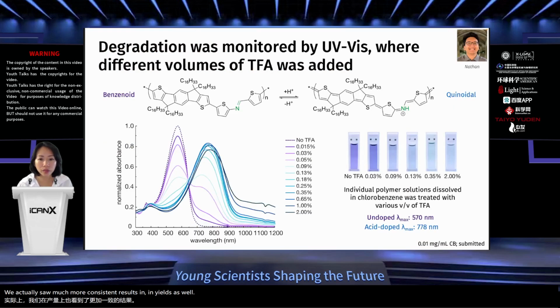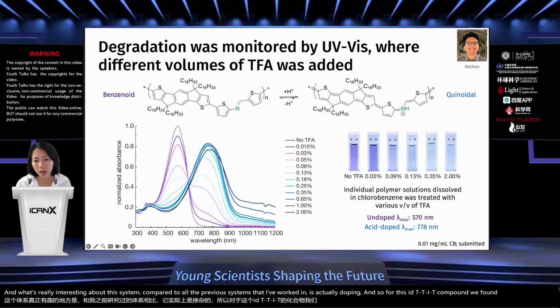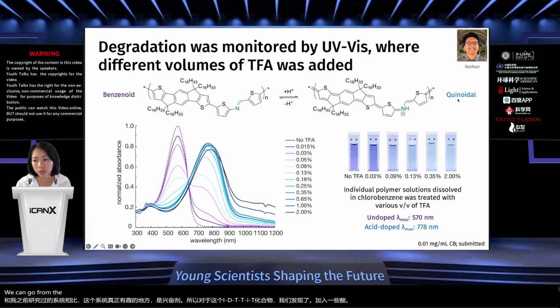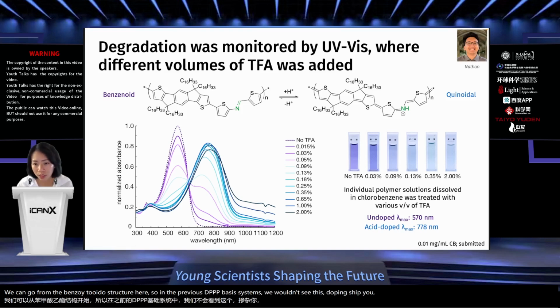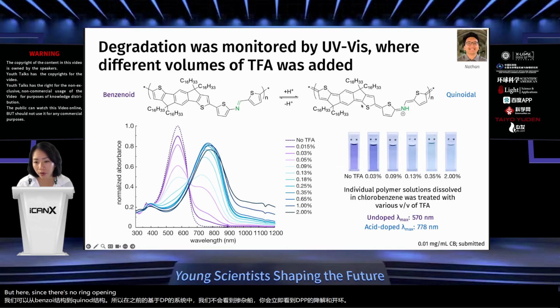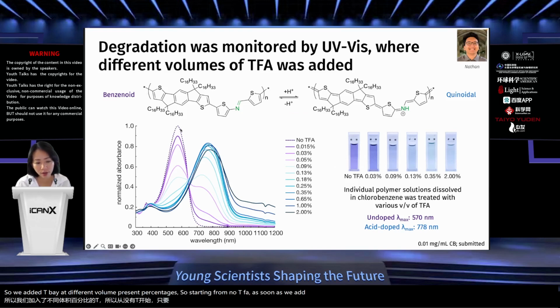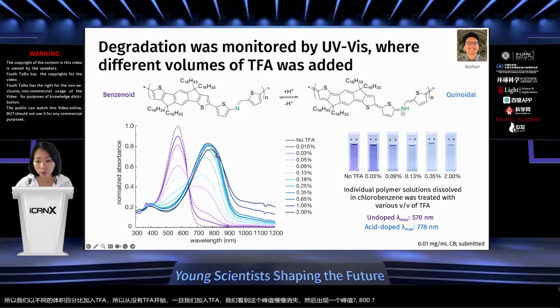And what's really interesting about this system compared to all the previous systems that I've worked in is actually doping. And so for this IDT-TIT compound, we found that upon adding some acid, we can go from the benzoid to quinoidal structure here. So in the previous DPP-based systems, we wouldn't see this doping shift. You immediately see a degradation and ring opening of the DPP. But here, since there's no ring opening within the IDT compound, we see this really nice doping that can be observed by UV vis. So we added TFA at different volume percentages. So starting from no TFA, as soon as we add TFA, we see this peak slowly disappear and the emergence of a peak around 800, which we are referring to as the dope peak.